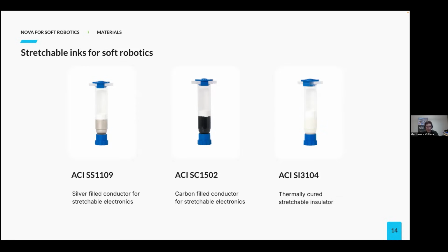Lastly is ACI's SI3104, and it's a white printable thermally cured ink that is stretchable after curing. It's specifically used as an insulator or can be used for crossover dielectrics. After curing, it has excellent durability, flexibility, and a high insulation resistance. It's designed for printing on TPU and again is fully compatible with the other two inks from ACI's stretchable line.